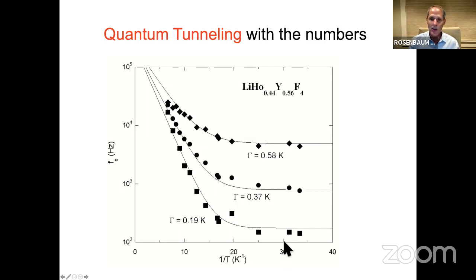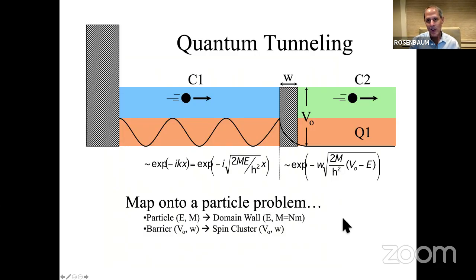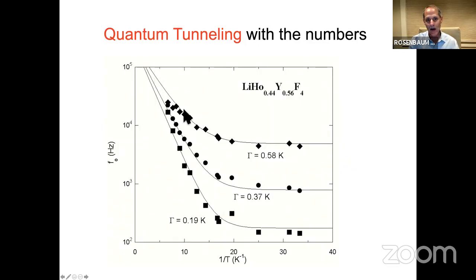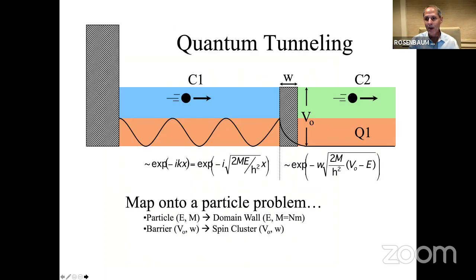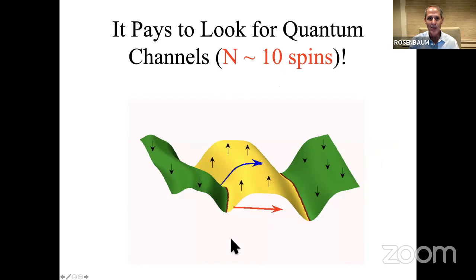And so what you can do now is take slices as a function of the quantum knob in the different regimes, okay? And what we do is map it onto a simple particle quantum tunneling model, where now the particle is the domain wall and the barrier is really the bunch of spins that are pointed in the opposite direction. And we just use a WKB approximation. When we solve for that, the solid lines here are a fit to this thermal plus quantum channels, where we assume they just work in parallel. And then we can solve for the mass of the domain wall, basically the number of spins. And we find that roughly 10 spins are tunneling at once.